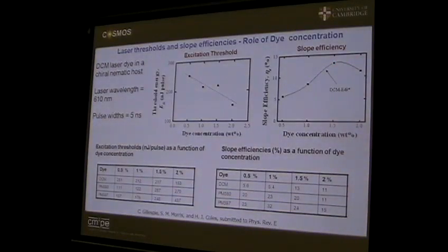So you do have to optimize your cavities, you do have to optimize the materials, the nematic and the fluorophore. But even with DCM, you start getting up to very high slope efficiencies, okay, 20, 23%, 32%, etc. Now that's with DCM. When I said DCM was a bad dye, so with a good dye, it gets better. Okay. When you bring down concomitantly, at the same time, you start bringing down your laser thresholds. Okay.